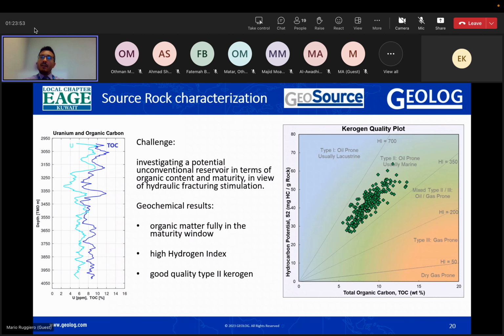And we plot the S2 against the TOC in this kerogen quality plot, and we see that all data points fall in a high hydrogen index region, which indicates a type 2 oil prone, usually marine. So we can assess the kerogen type, and we know that it's a good quality type 2 kerogen.